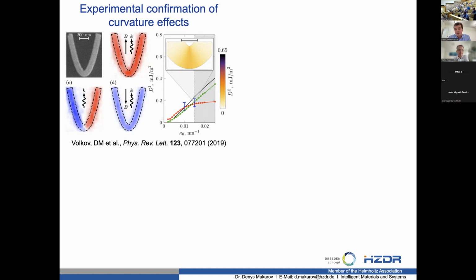And you can quantify this effect. Even in symmetric stacks of centrosymmetric materials, like, for example, permalloy, you can have a very strong Dzyaloshinskii-Moriya interaction-like effect at the apex of a geometrically curved stripe, like in this case, a parabola, which is as strong as you have in, for example, very precisely engineered out-of-plane magnetized cobalt-based asymmetric sandwiches for skyrmion research. This is already a very interesting tuning knob which the material science or physics community can obtain if you play with geometry. So you can induce rather strong chiral responses by tailoring the geometry of magnetic thin films.